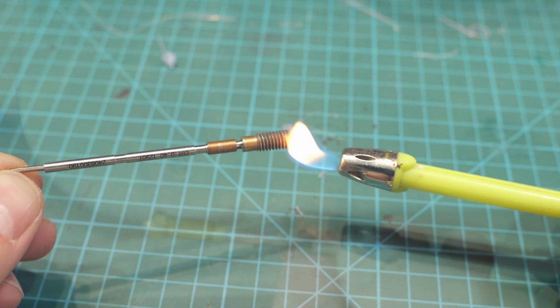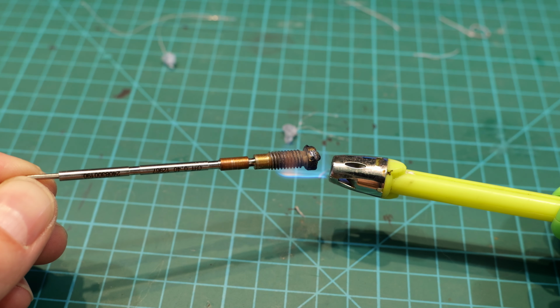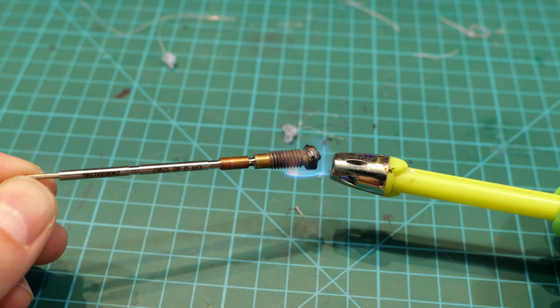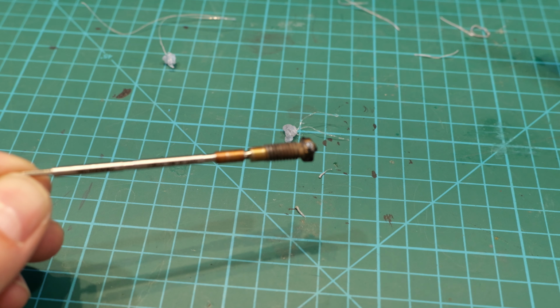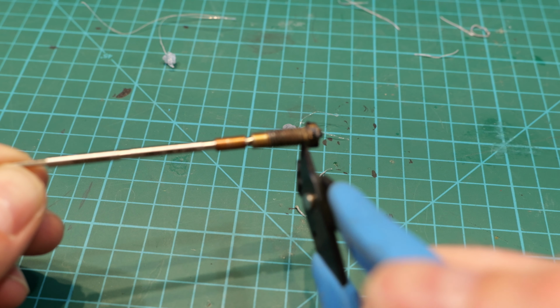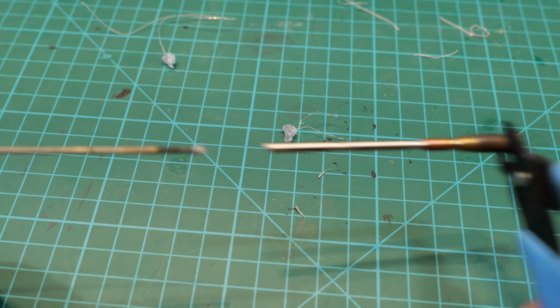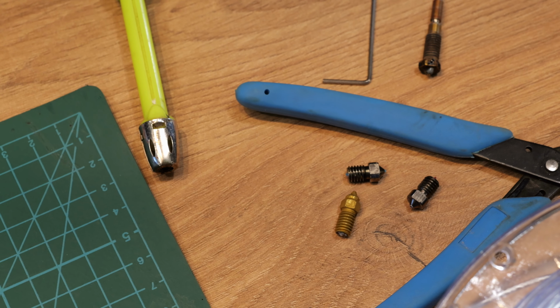One big mistake people make is using a torch instead of a lighter. A torch can get too hot for the brass and you can damage your nozzle, especially if it contains extra parts inside, like high flow nozzles or ruby nozzles, etc. If you are still not able to unclog your nozzle, then probably you should just replace it.